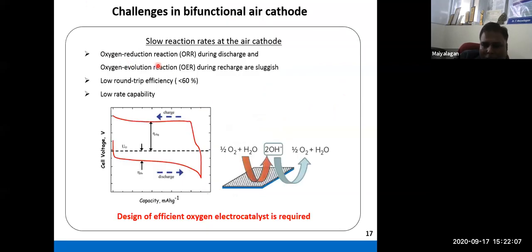So the oxygen reduction reaction takes place. You just have a metal and air. Air is available freely, and from air you get oxygen. From the oxygen, oxygen reduction takes place during discharge, and oxygen evolution takes place during recharge. And both reactions are sluggish. Sluggish means very slow reactions, and that's why you need a better catalyst to improve the performance of the oxygen reduction reaction during discharge and the oxygen evolution reaction during recharge.